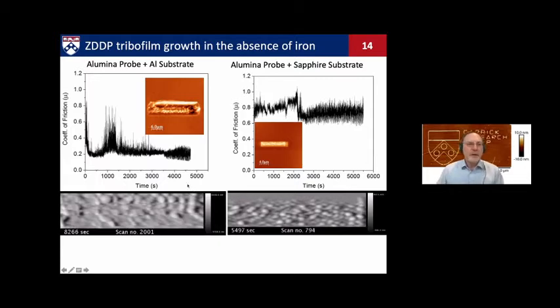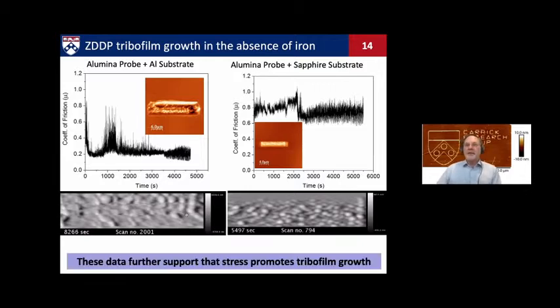So we can grow ZDDP on aluminum and aluminum-based substrates, but then we're surprised, how was it that we got it on these materials? And in particular, we saw that there was a lot of damage to the aluminum substrate after the tribofilm had grown. You can see some buildup here and almost like a trench surrounding the tribofilm. In fact, what we observe is that the first part of the experiment didn't actually involve growth. It involved just deforming the aluminum substrate plastically. So while this does support that stress promotes tribofilm growth, the aluminum is soft.